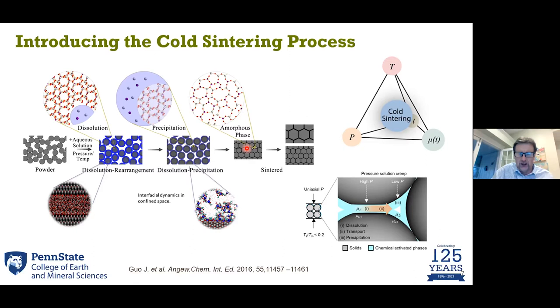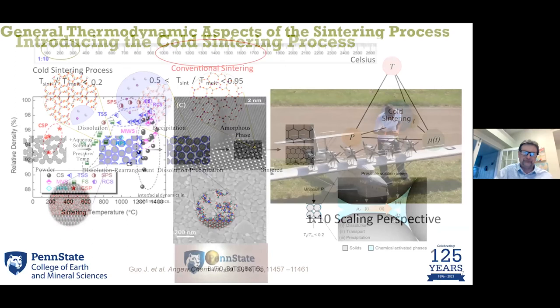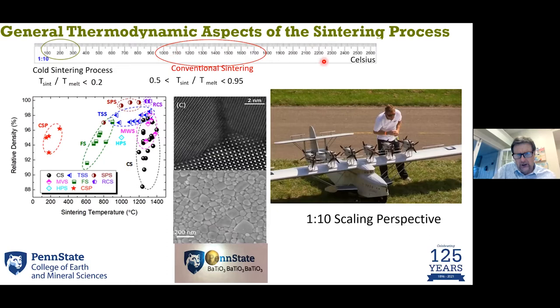also very short times. And so these dynamics of really low temperatures, apply pressures, moderate pressures, anywhere between 70 megapascals to 500 megapascals, not gigapascal levels, the activity, the all-important chemical activity at the time is critical to this densification process. So if we consider like a scale here in terms of Celsius, most sintering of oxides are in this range, 1,000 to 1,700. The cold sintering allows us to work right down here. So it's like a 10 to 1 ratio.